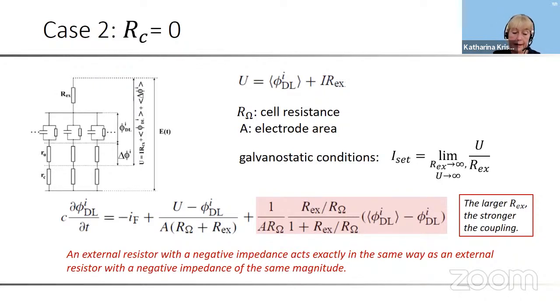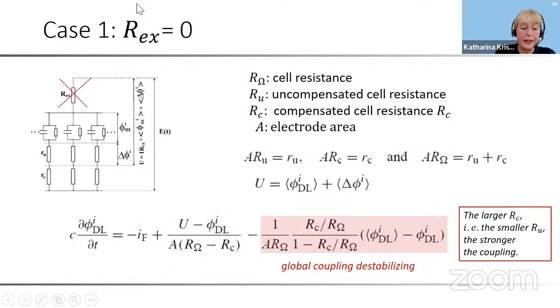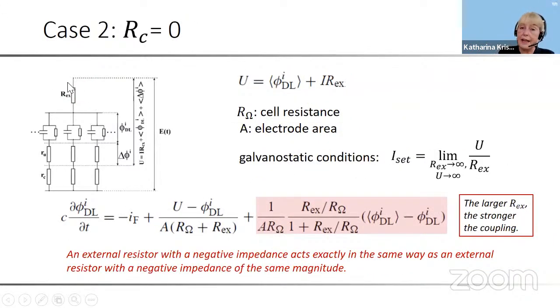And if you compare this expression with the other one that I obtained in the presence of some uncompensated resistance, you see that an external resistor with a negative impedance acts exactly in the same way as the compensated resistance before. In other words, if we would have here a negative impedance device which would act like a negative resistor, we would obtain the same dynamics as we do when we compensate part of the cell resistance.